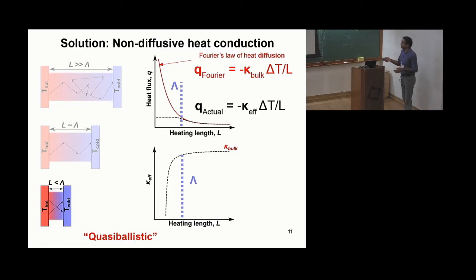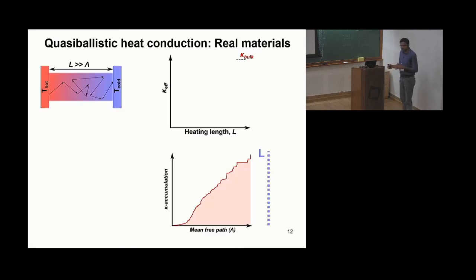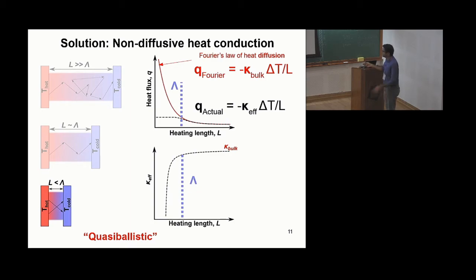So this is a hypothetical material where all phonons have only one mean free path, and this is what you would see in an experiment when you measure thermal conductivity. Now what happens in a real material? I'll show some data later. I'm just exaggerating the curve here, but you will see that thermal conductivity is no longer a property of a material, but changes with length scale in this manner.